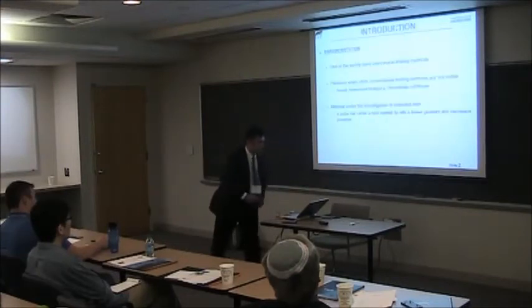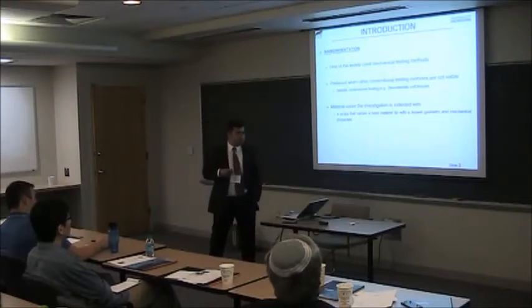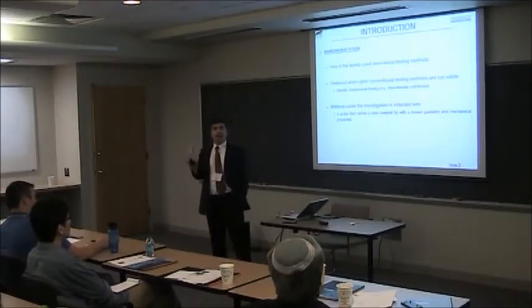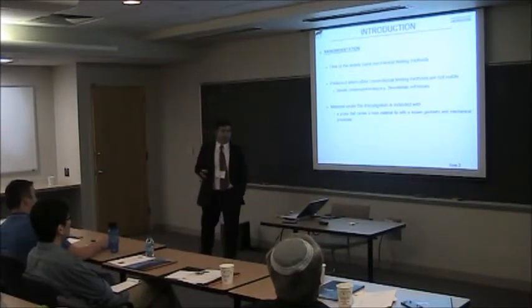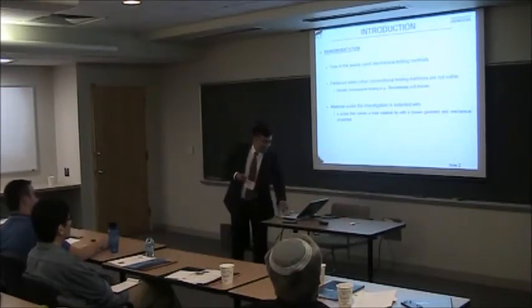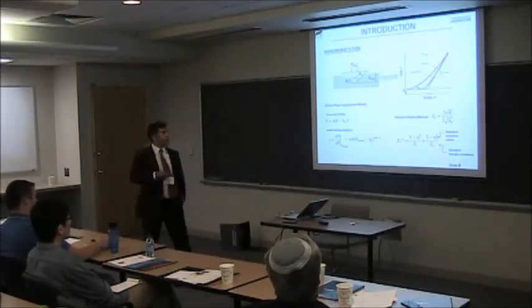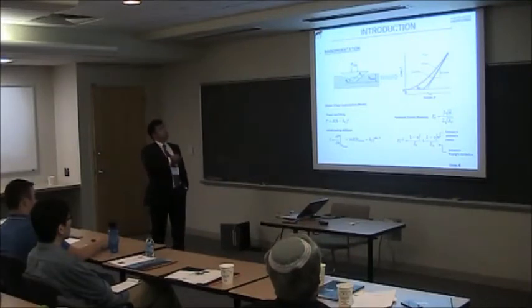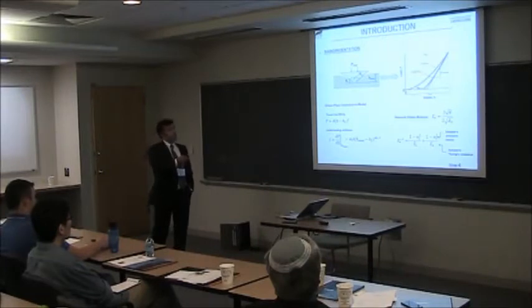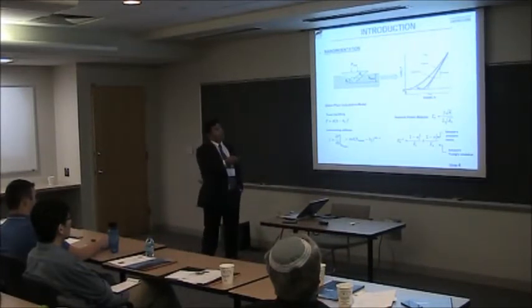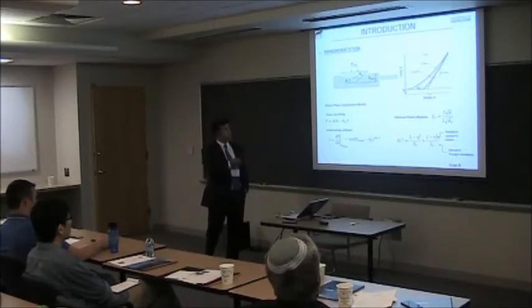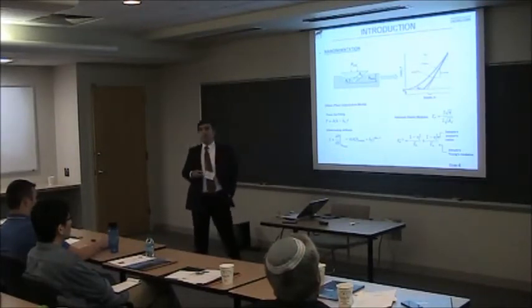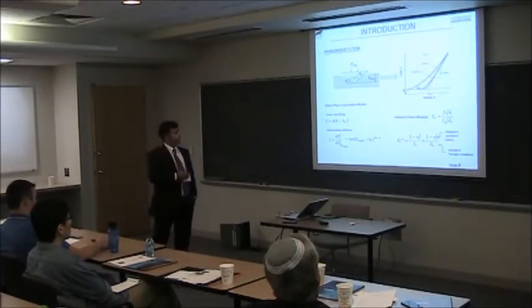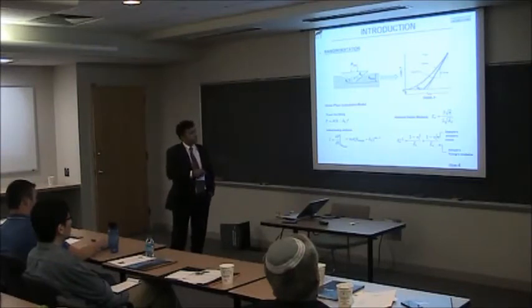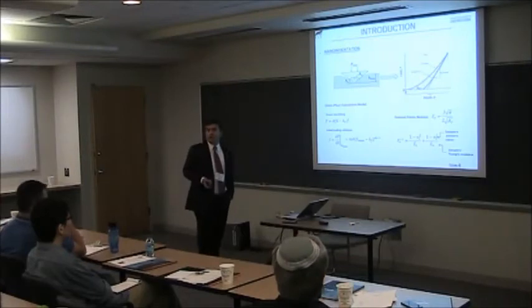So Kit actually touched upon how AFM tips are not good for nanoindentation. And obviously, there are models. This is Oliver Pharr that he showed. What you do is you indent on a material, you pull it back slowly, and you look at how much you can get in, which is the H max. And then at that point, you measure the maximum force, and then you slowly pull it back. And now you see that you have the slope. Slope gives you the stiffness. And then at the end, if you have plastic deformation, then you have HF, which, through the force calculation, will affect your Young's modulus. So that was the main idea that we were doing.